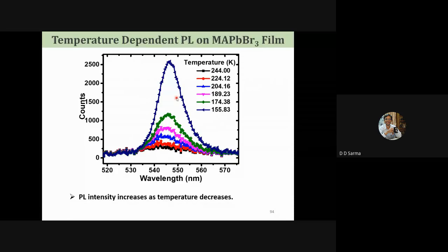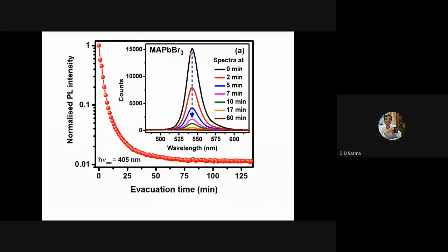One of my clever students actually started doing the experiment without changing the temperature as she was evacuating. And she found as soon as she starts to evacuate, the intensity is going down, and going down very rapidly. Here in logarithmic scale, with the pumping time, the intensity dropped off. That means something very unusual is going on with evacuation.